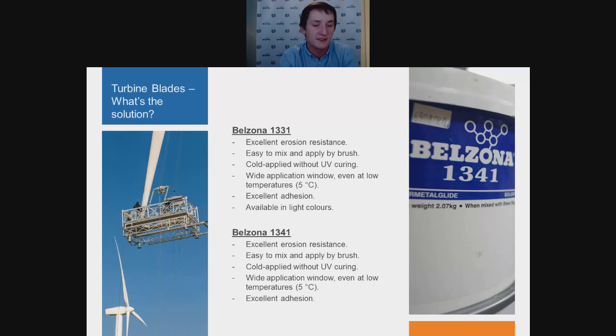They both have an excellent adhesion onto the GFRP. So in most cases, when we do an adhesion test, the GFRP will break cohesively before the Belzona materials come off adhesively. The other important application or benefit you want from your leading edge protection is ease of application. This is very often going to be done in the field, often hanging off of a rope or on a platform like the gentleman you can see on the left. So you want it to be nice and easy and quick to apply. So both of these materials are very easy to mix, just simply in a bowl, and they can both be applied by hand with just a brush.